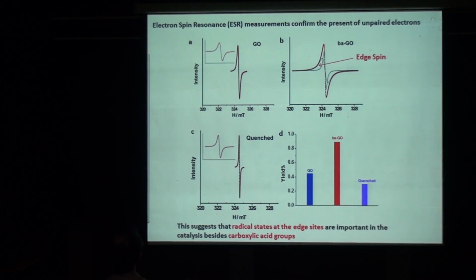This is how we know. We performed the electron spin resonance study. At the edges of these holes, maybe they have the non-bonded pi electrons. The non-bonded pi electrons, dangling bonds, unpaired electrons, highly reactive at the edge. Because if you perform electron spin resonance on a normal graphene oxide, which has not been subjected to the same treatment, we see a very sharp signal.